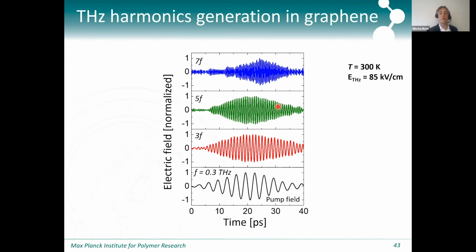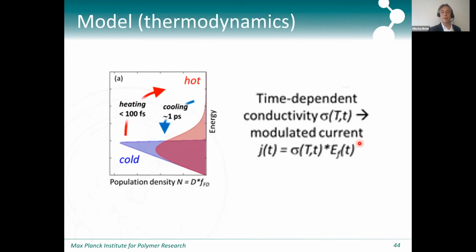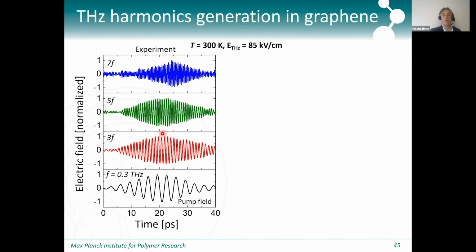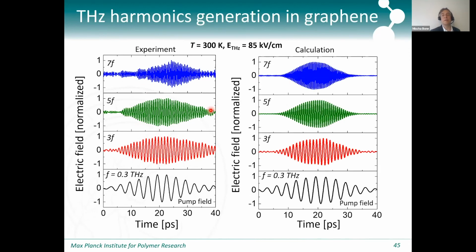So here you see a filtered version of the third, the fifth, and the seventh. So we Fourier filtered and windowed the traces that we measured to highlight the different harmonics. And so we can again use our simple model because we now know how, when we heat the electrons, the conductivity changes and how rapidly it cools. We've measured that independently. And so that simple model actually reproduces the data quite well.